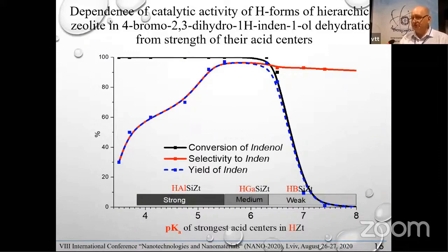As we can see from this picture, there are quite narrow fields of optimal acid center strength for achievement of high yield of indene, because in the case of stronger centers, we can obtain a very large quantity of side products. In the case of weaker centers, we cannot achieve high conversion.